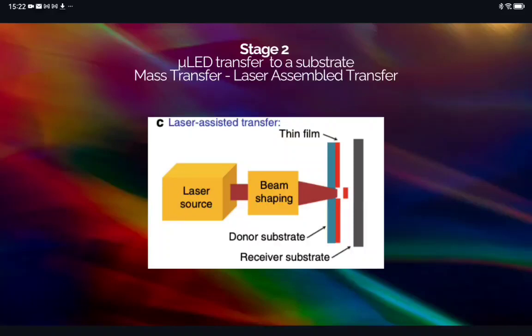The next method is laser-assisted transfer. This method utilizes a laser to transfer and place discrete micropads onto a receiving substrate. The micro-LED release process is driven by the thermomechanical response of the dynamic release layer under laser irradiation. The number of micro-LEDs that can be placed is about 100 million microchips per hour. The placement error is about 1.8 micrometer for 50 times 50 times 6 micrometer devices. The high accuracy and efficiency make this method often used in micro-LED commercialization.